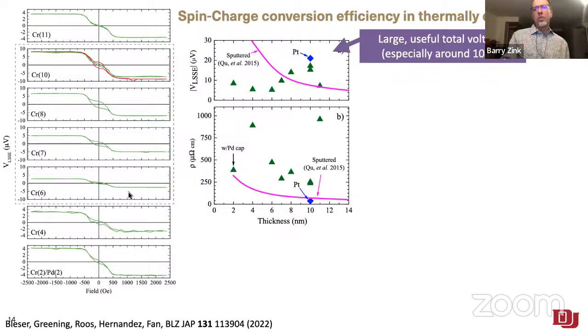We saw this very different non-monotonic behavior, first in the raw voltage as a function of thickness. You can see the green triangles are our data. That's compared to our 10 nanometer thick platinum film. This blue or pink line is the sputtered case there. So you can see this 1/T thing that we didn't get. It doesn't correlate perfectly with the resistivity. It turns out the resistivity of this stuff kind of jumps around all over the place. That's also relatively common with chromium. Chromium's kind of weird in that respect. There's a whole lot of complication there that we won't go into. But the point is that there's no simple explanation of this non-monotonic peak that comes from resistivity.